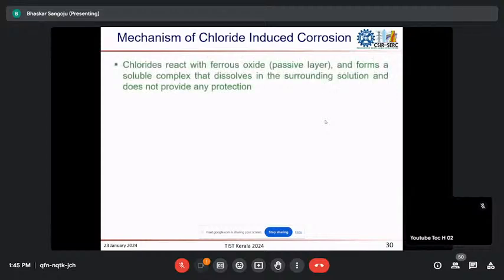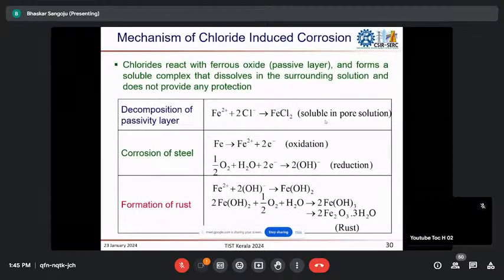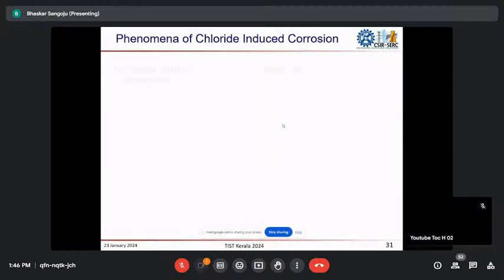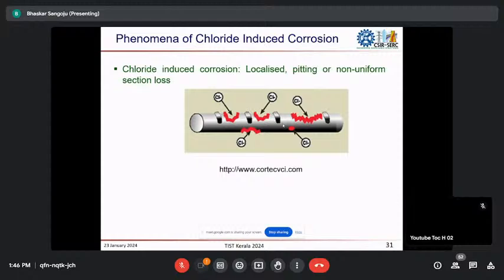But in the case of chloride induced corrosion, it will not be like this. There a pitting type, localized corrosion we can see. So here in the chloride induced corrosion, this is the mechanism that is taking place. First, chlorides react with ferrous oxide, that is the passive layer, and it becomes ferrous chloride. This is soluble in pore solution. Then the passive layer becomes unstable, depassivates, and corrosion of steel starts, and later formation of rust products. So in chloride induced corrosion, it is more localized. Wherever the concentration of chlorides is more, there the rebar will get corroded. So it is more localized, pitting type.